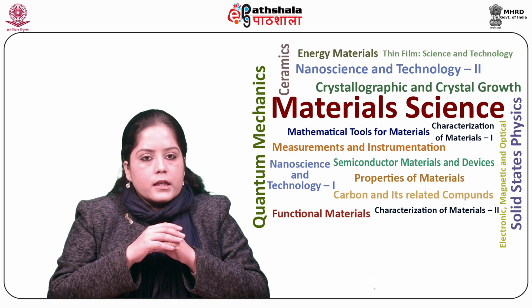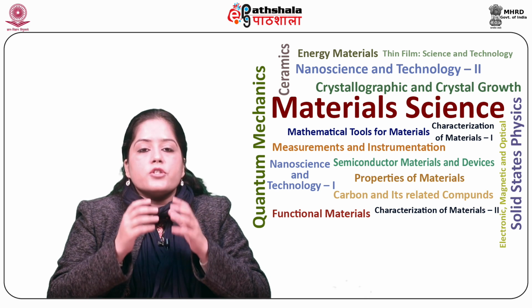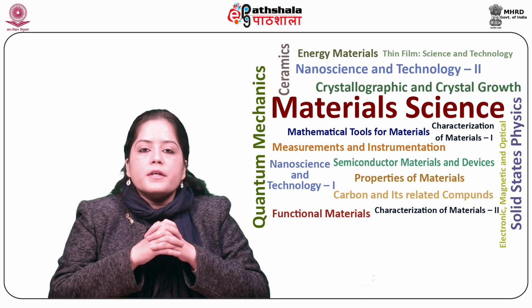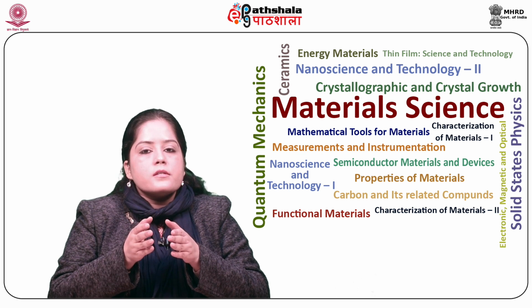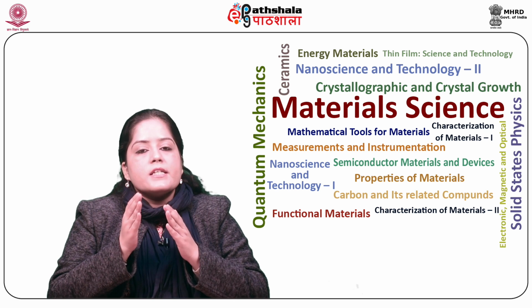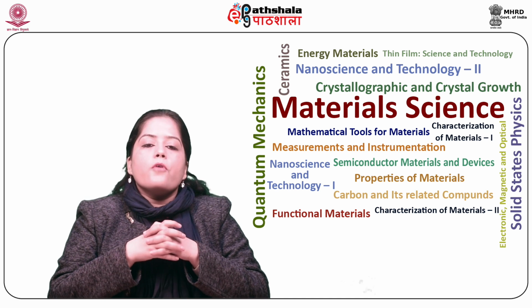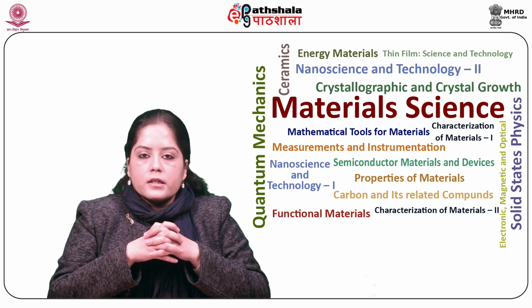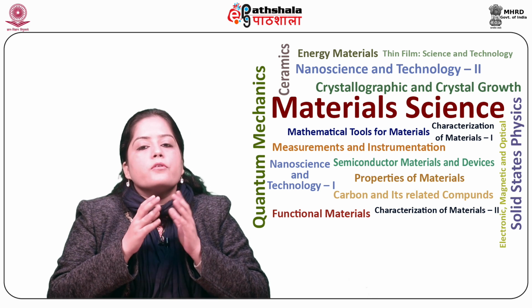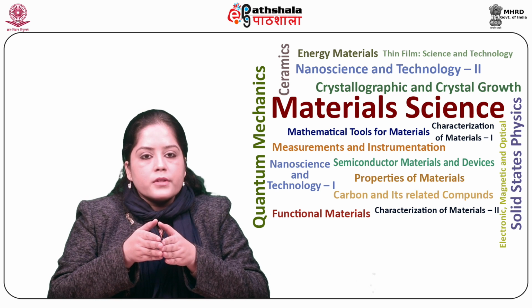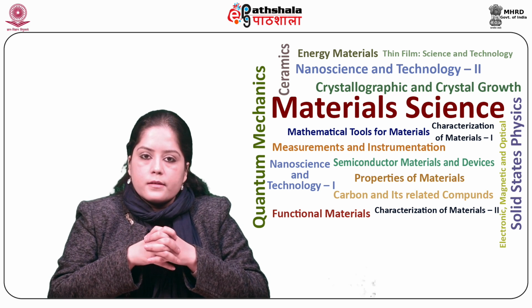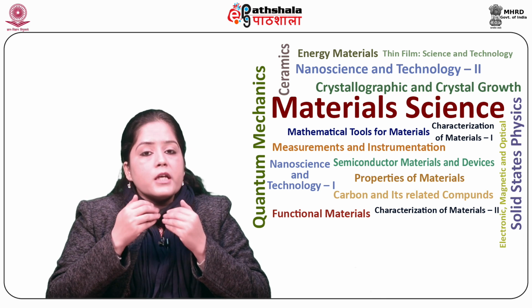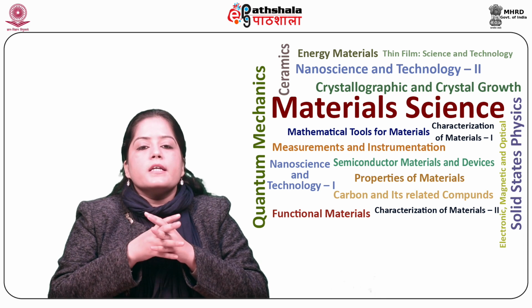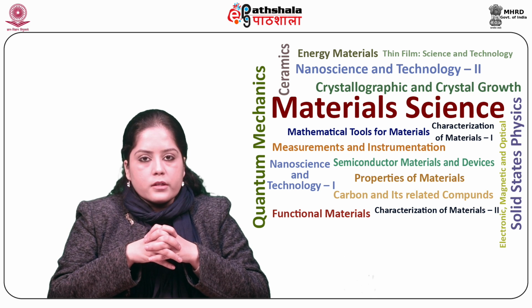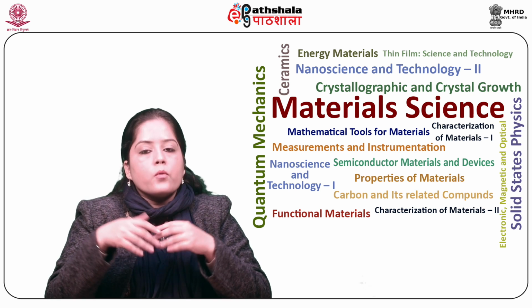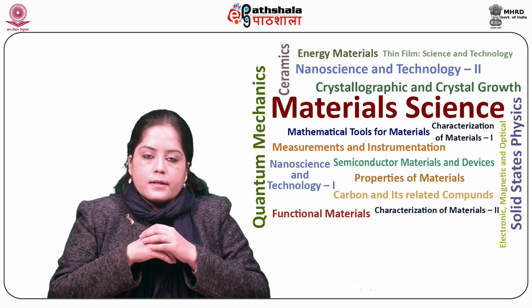The length scale corresponding to the regime of quantum confinement ranges from 1 to 25 nanometers for a typical semiconductor of groups III to V and II to VI, in which the spatial extent of the electronic wave function is comparable with the particle size.